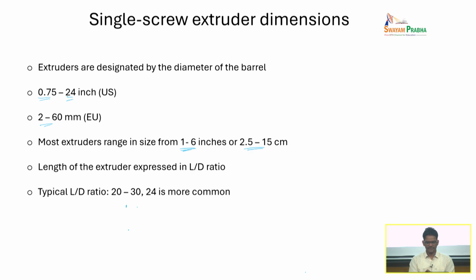And then the length of the extruder is expressed in terms of L by D ratio. L by D is nothing but the length of the barrel divided by the diameter of the barrel. It's like an aspect ratio. And this ratio can be anywhere between 20 to 30, and 24 is a kind of standard size. So when we say 20, it means the length of the barrel is 20 times more than the diameter of the barrel. That's the aspect ratio.